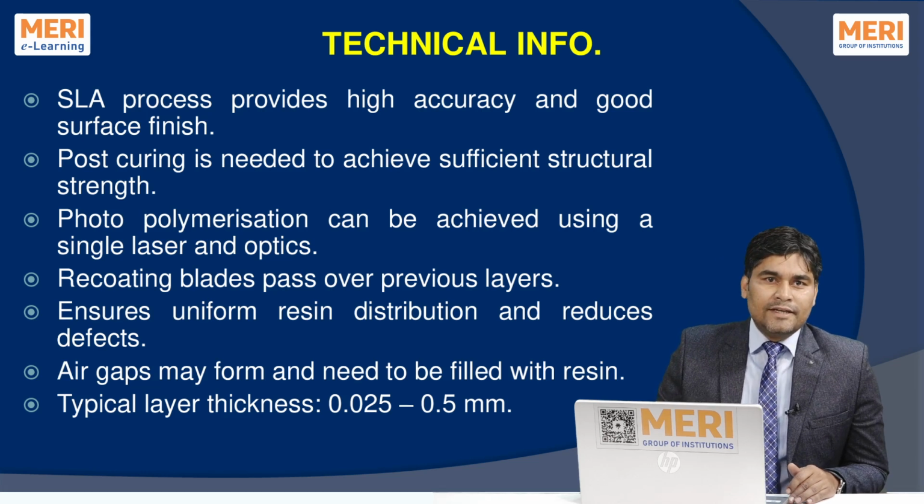Typically, the layer thickness ranges from 0.025 mm to 0.5 mm, where thinner layers provide better accuracy but increase printing time.